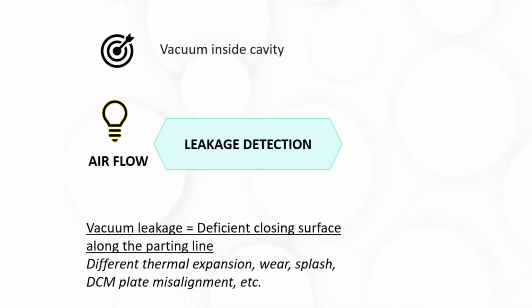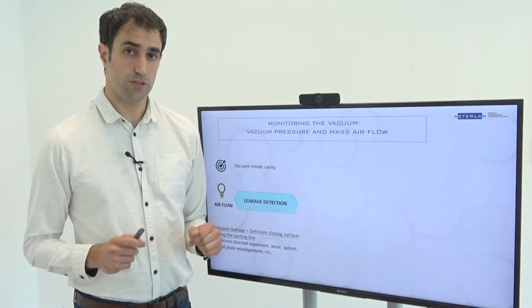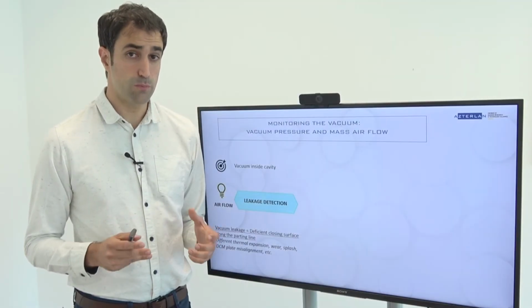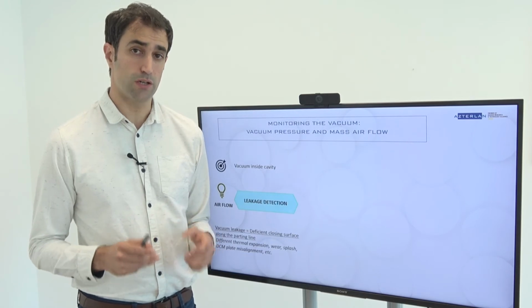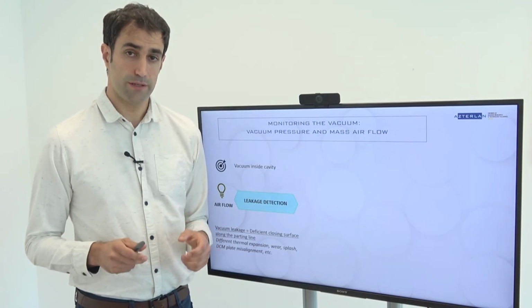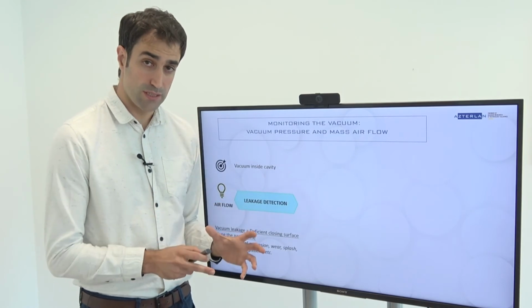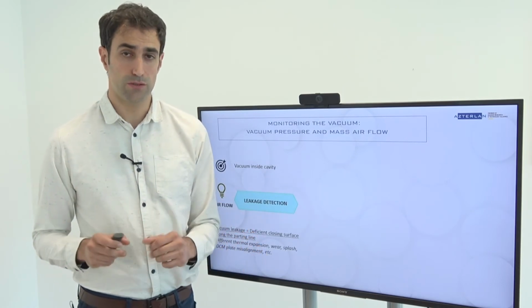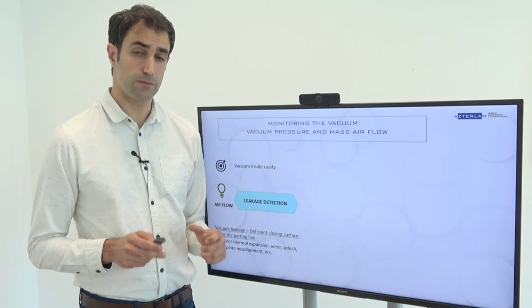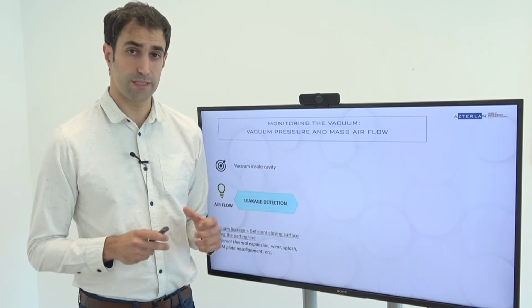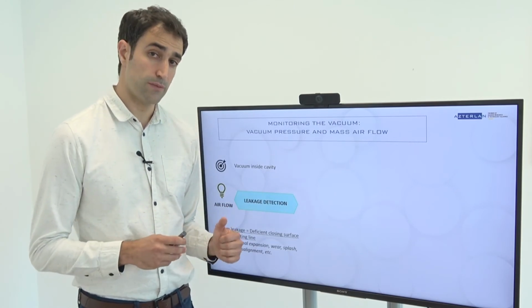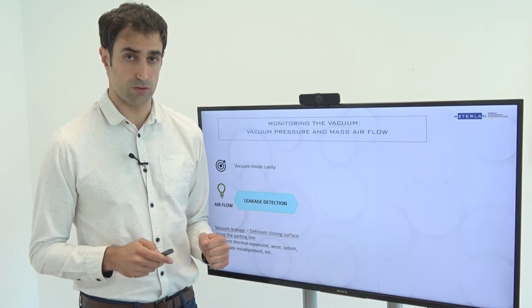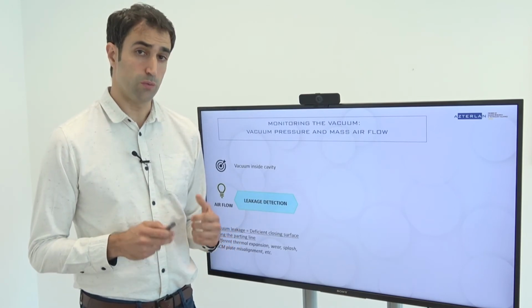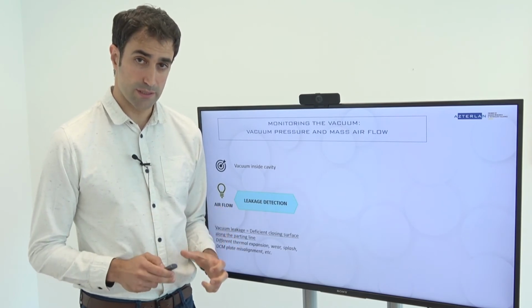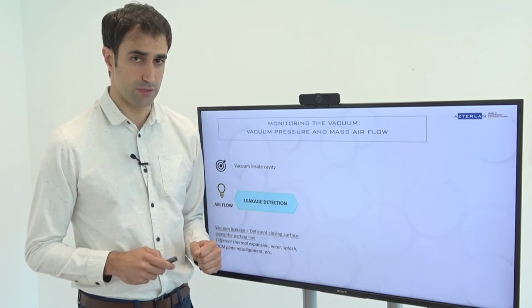When it comes to vacuum, the target is a certain vacuum level inside the cavity. So the question is, what is measured and where? Vacuum pressure is always measured, but usually only in the pipe. However, the reality is that vacuum in the pipe is very different from vacuum inside the cavity. That is because one of the major problems with vacuum is leakage, which comes from a deficient closing surface along the parting line. So, when we cannot measure vacuum inside the cavity, airflow monitoring can give us valuable data, like